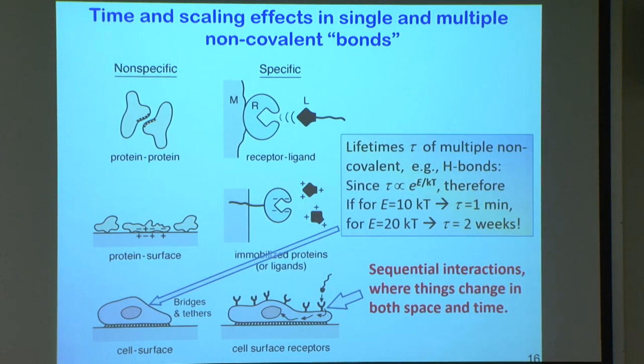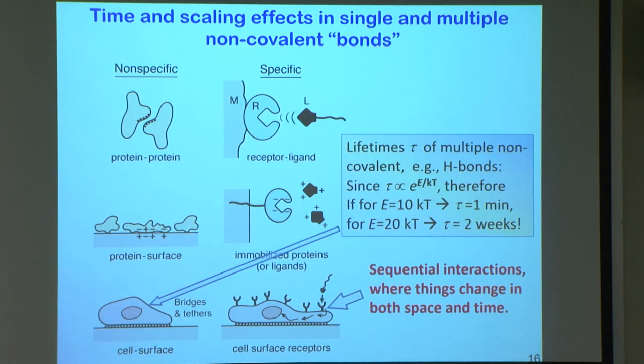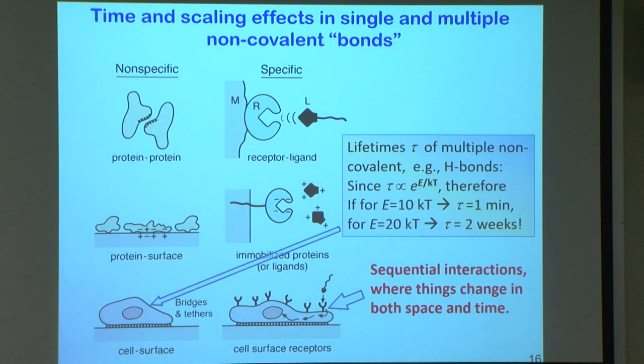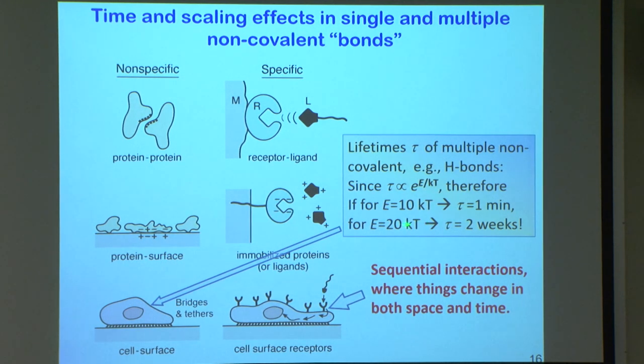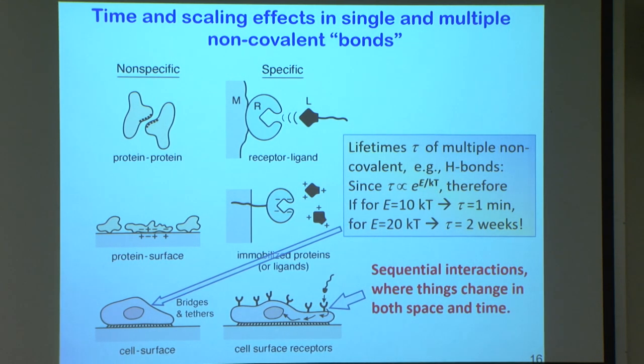If you have a certain energy, like 10 kT, which is a typically strong hydrogen bond, the lifetime of that bond could be a second or a minute or something like that, which isn't unusual. If it's 1 kT, it'll be nanoseconds. But if it's 20 kT, so just two bonds in contact, or one bond of twice the energy, this goes to two weeks. So you can double the energy of an interaction, but the lifetime of that binding can increase by orders of magnitude. The energy and the time scale vary very differently, as does the number of bonds. One bond and two bonds are very different.